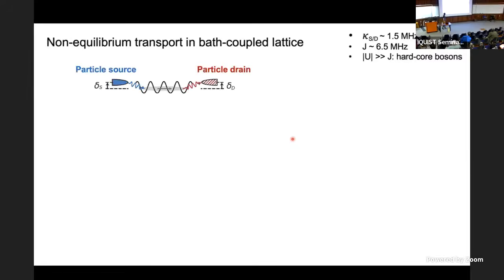Okay. So this is the setup that we want to cover, right? So bath-coupled transport in this Bose-Hubbard lattice. And in the experiments I'm going to show you, we will keep the source and drain at the same energy, okay? And move them up and down together with respect to the lattice. And we're going to measure the steady state, or measure the currents by measuring, for example, the link at the middle of the lattice.